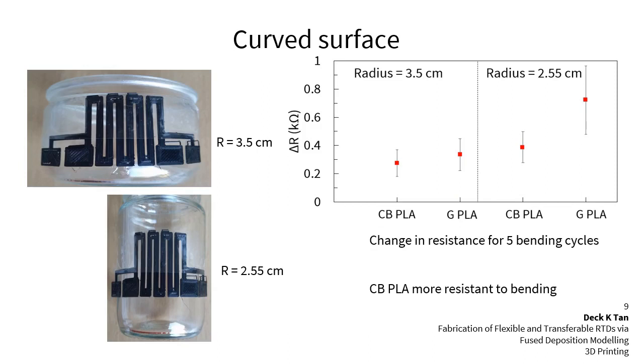Then the 3D printed sensors were peeled from their mylar substrate and transferred to two curved surfaces of different radii. So this shows the transferability and the stability of the sensors when measuring their resistance on curved surfaces. The two curved surfaces have radii of 3.5 centimeters and 2.55 centimeters. The measurements were taken at room temperature for this test.